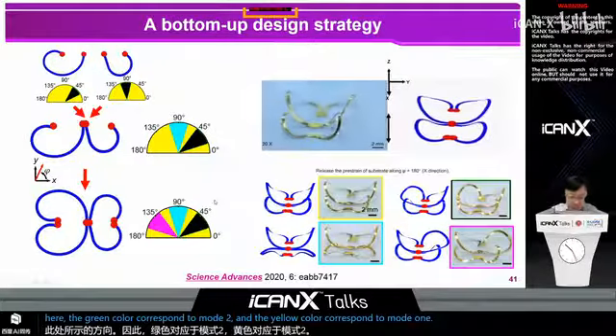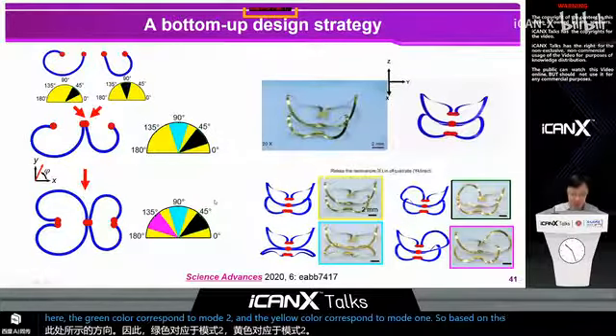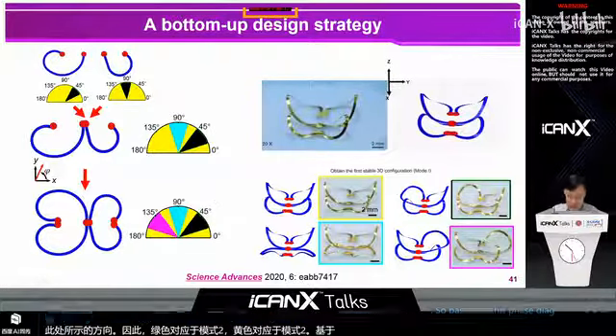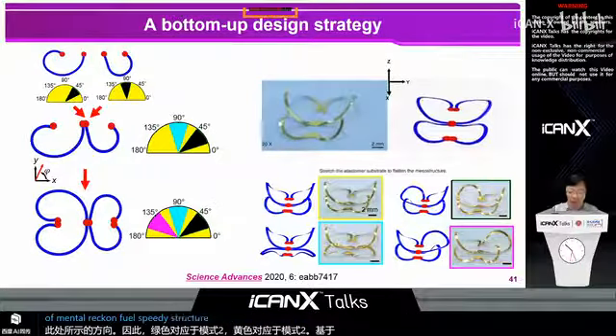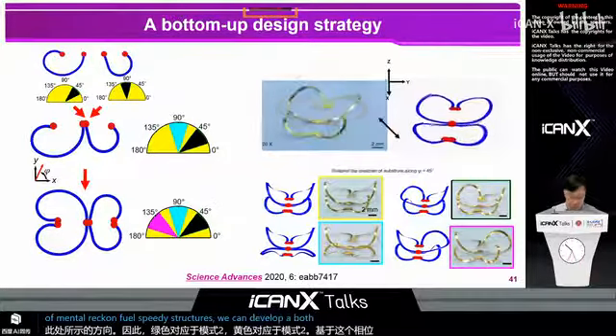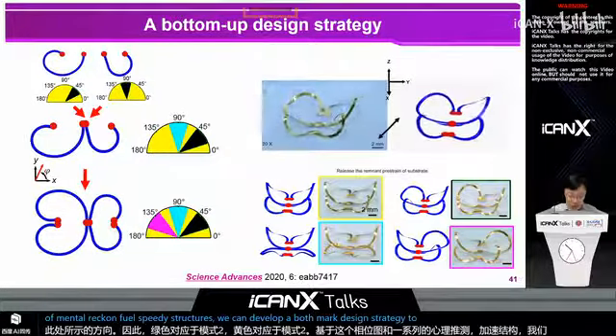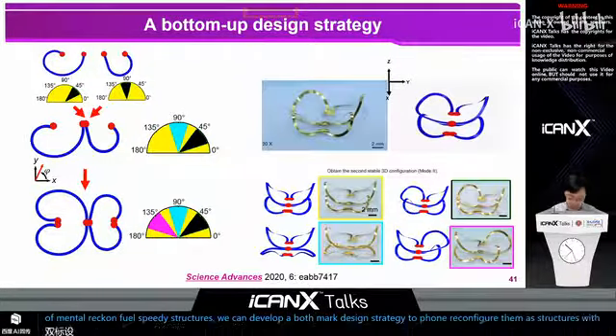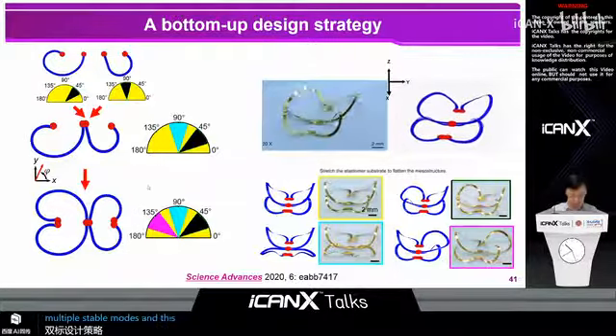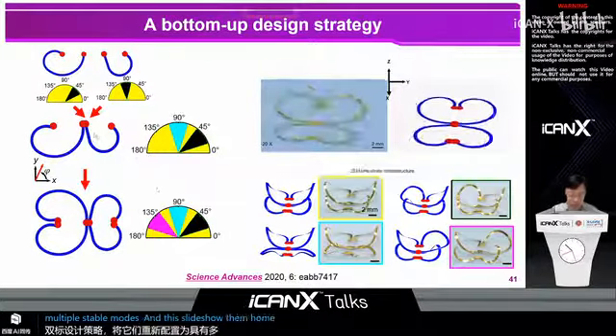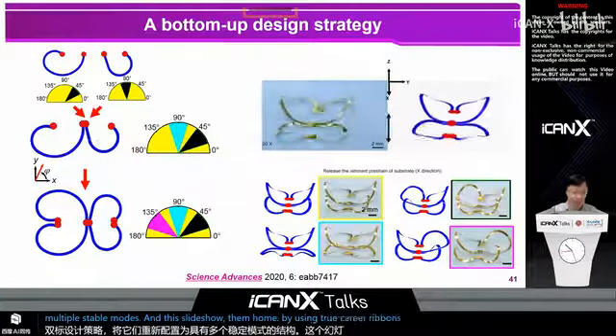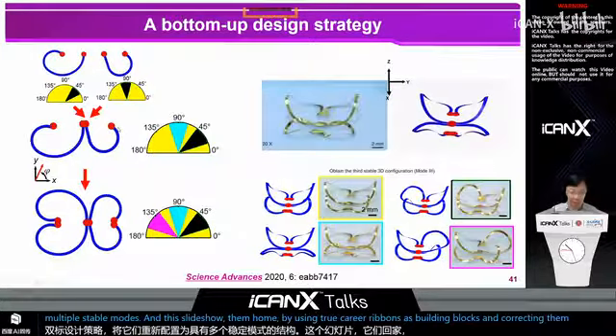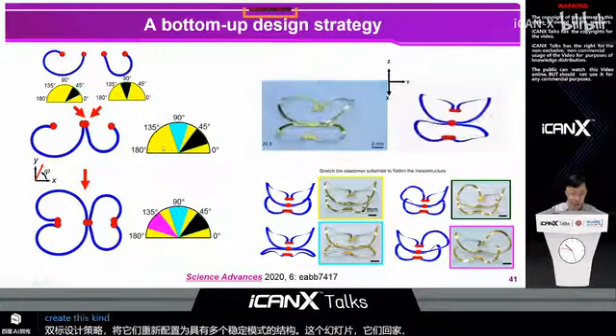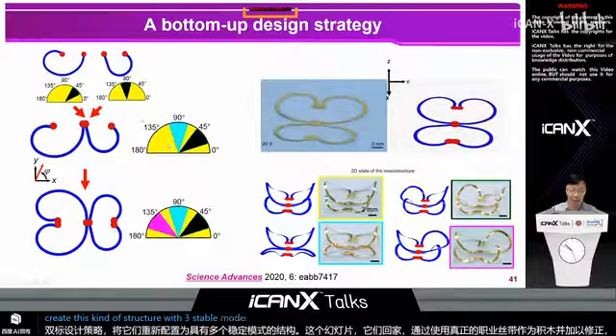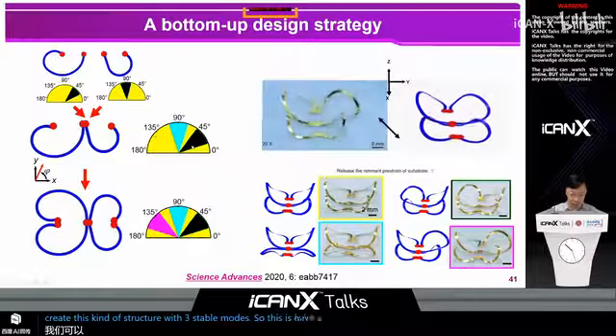So based on this phase diagram and a set of fundamental reconfigurable 3D structures, we can develop a bottom-up design strategy to form reconfigurable mesostructures with multiple stable modes. And this slide shows an example. By using 2 curvy ribbons as building blocks and collecting them together, we can create this kind of structure with 3 stable modes. So this is evidenced by this phase diagram.